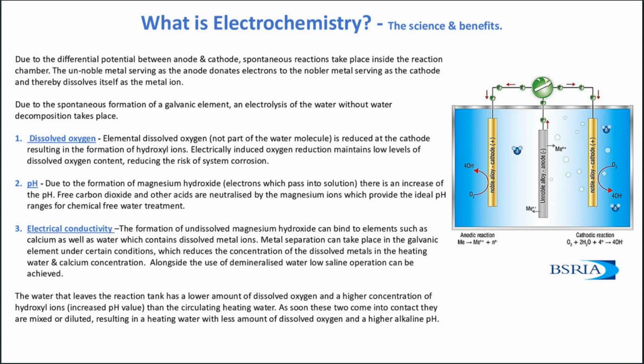Free carbon dioxide and other acids are neutralized by the magnesium ions, which provide the ideal pH ranges for chemical-free water treatment. Electrical conductivity. The formation of undissolved magnesium hydroxide can bind to elements such as calcium, as well as water which contains dissolved metal ions. Metal separation can take place in the galvanic element under certain conditions, which reduces the concentration of the dissolved metals in the heating water and calcium concentration. Alongside the use of demineralized water, low saline operation can be achieved.